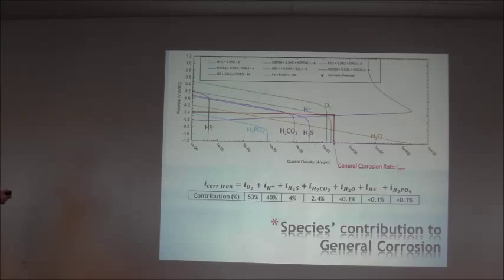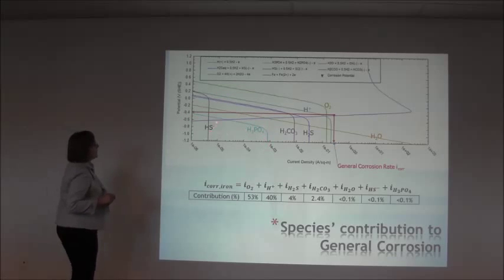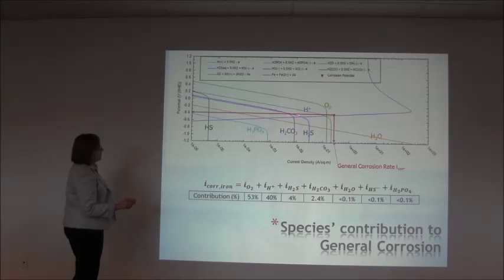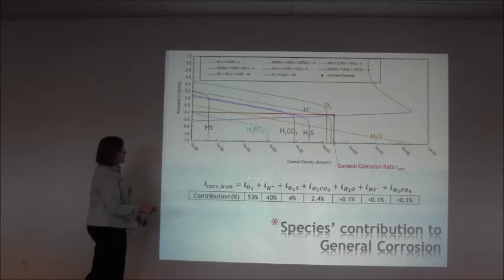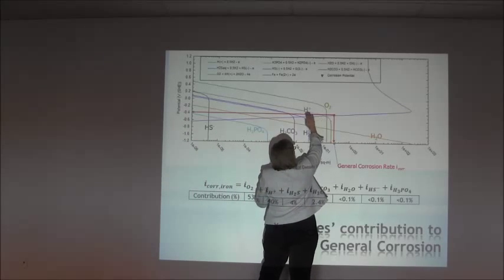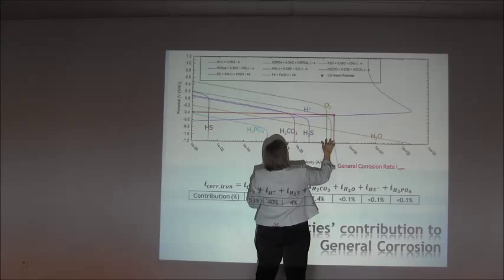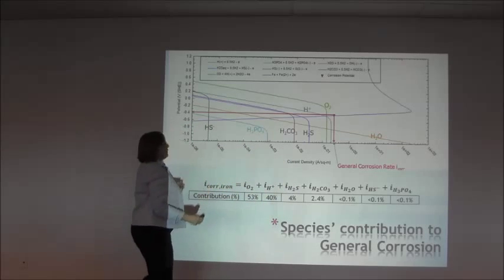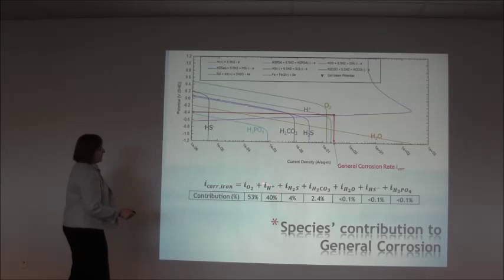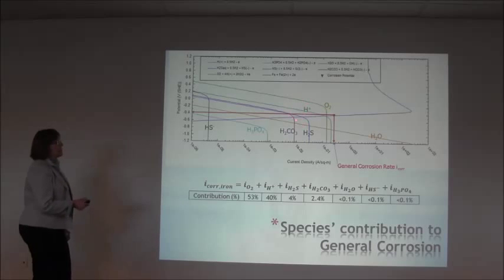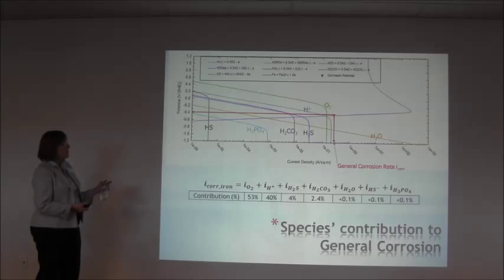Polarization curves are very hard for me to understand, but each one of these lines is connected to an ion constituent. As they drop, that's the limit of diffusivity. Because we calculate that fully speciated model, each of those lines is basically saying how far the ion is going to hit the wall before it stops. If you take the line that's furthest out, this is the H ion and this is the O2, these two lines, which are the two free concentrations in the solution, are causing 53 plus 40%, 93% of the corrosion at this point, due to H plus and oxygen. Well, H plus, that's low pH. So that's how you read the polarization curve.